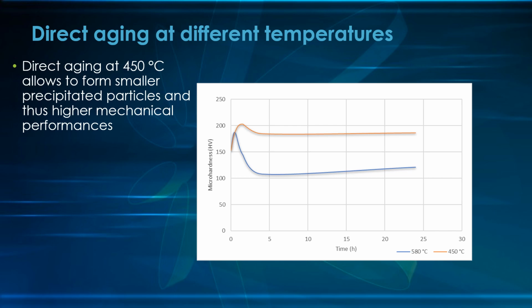This is due probably to the formation at lower temperature of nanoprecipitates. So that means that we have formation of nanoparticles able to hinder dislocation movement and able to increase the mechanical properties of the alloy.